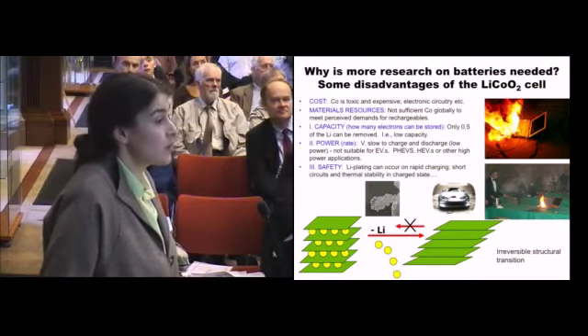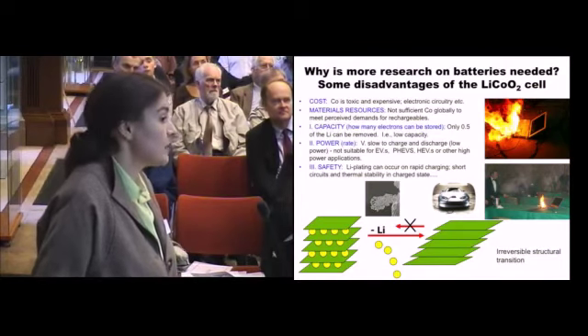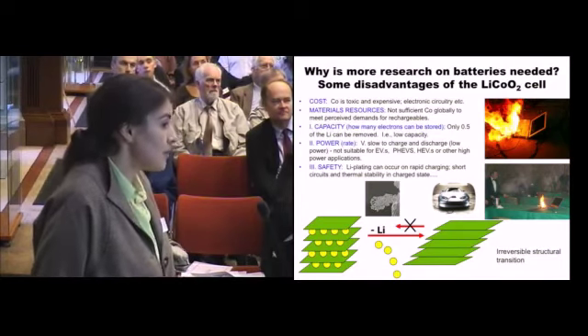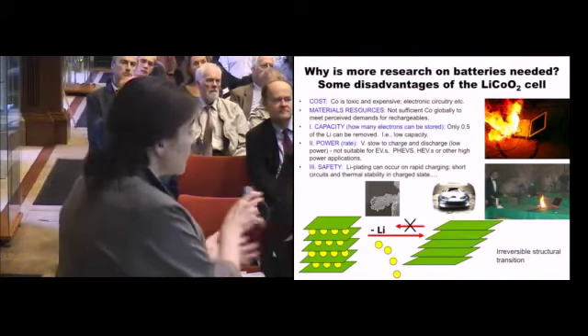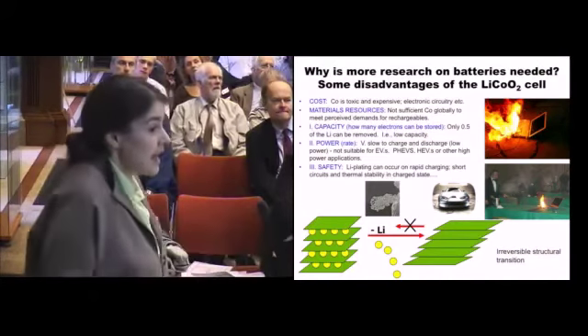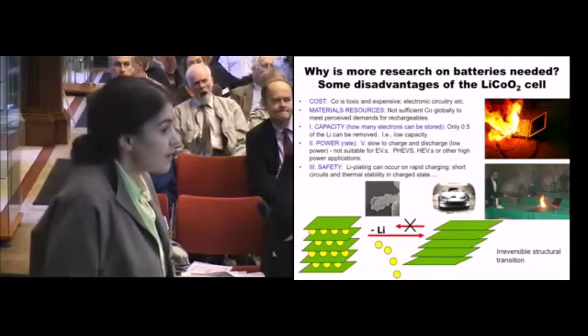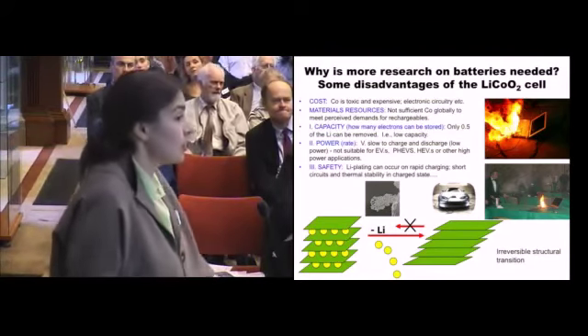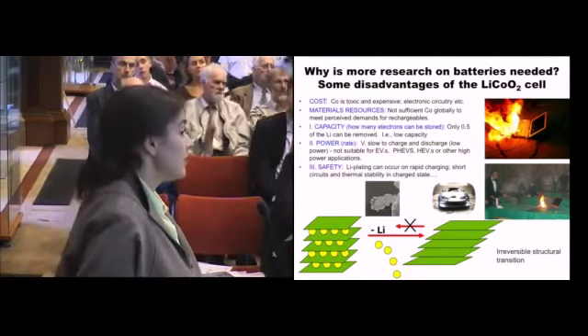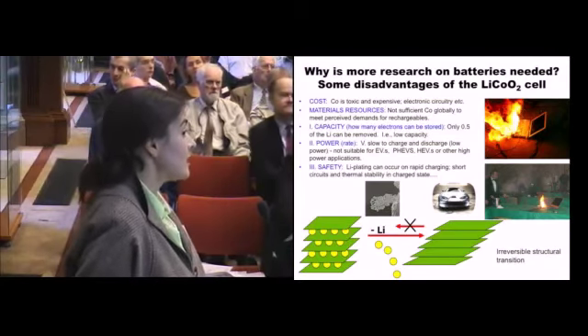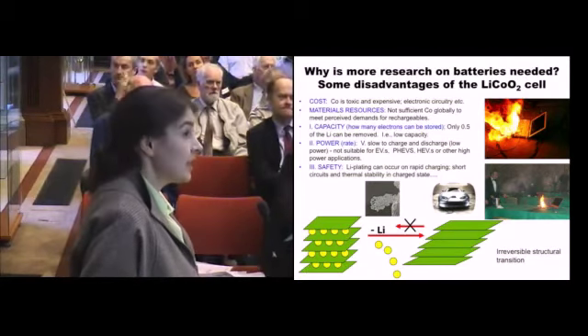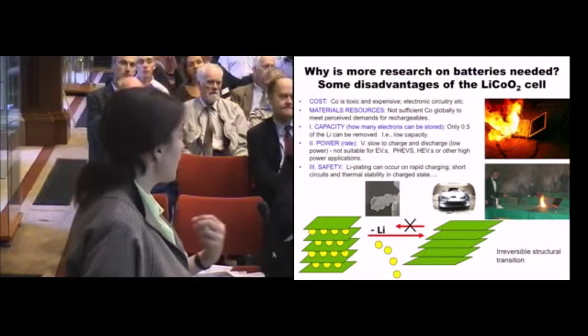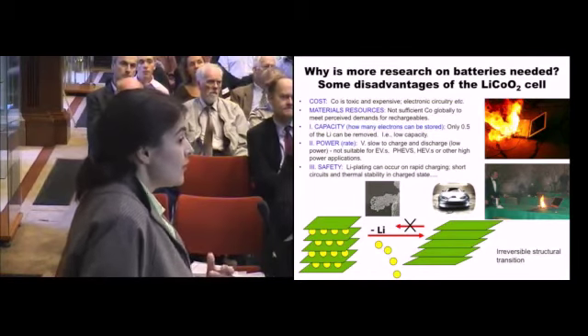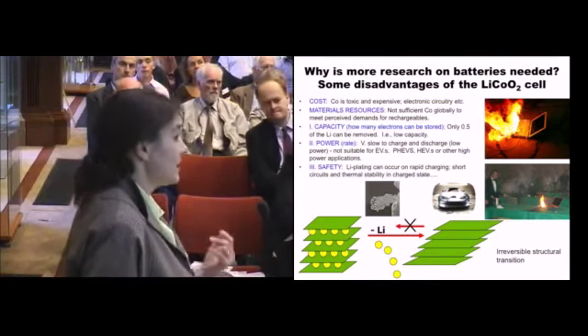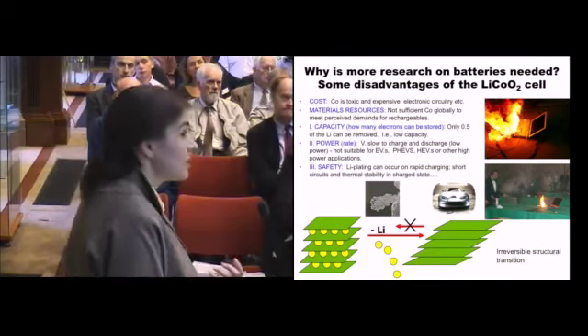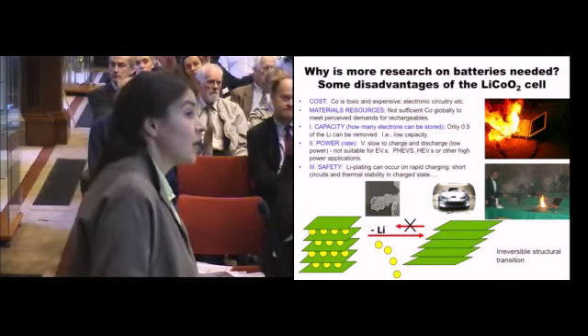And it's an interesting one in this material. So you take your layered material, and if you pull all your lithiums out, what actually happens is the layers shear, so they slip, and then you can't get the lithiums back in again. So it's no longer reversible. So what you do in practice is you leave about 50% of the ions there to allow this reversibility. So you're not actually getting the full capacity out of this material. So if you could figure out how to get all of these lithiums out, you'd have a battery that could essentially last twice as long.